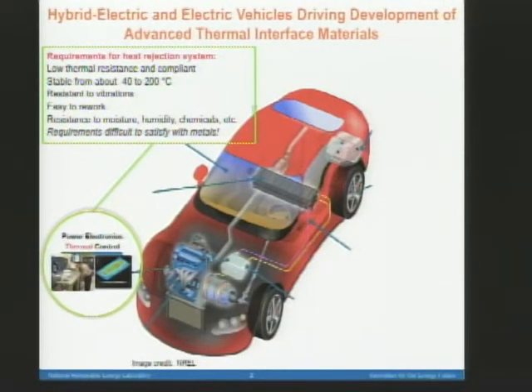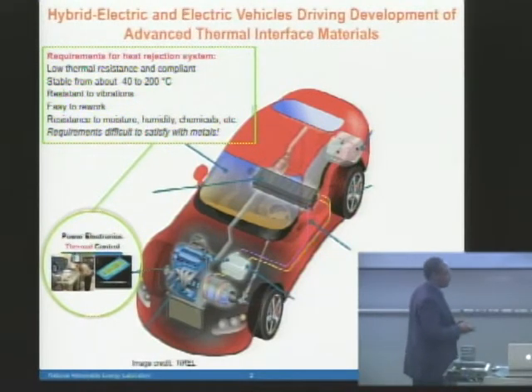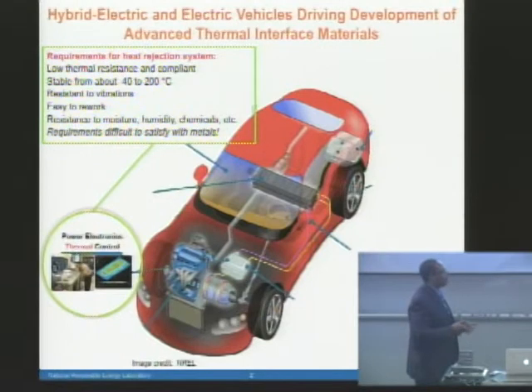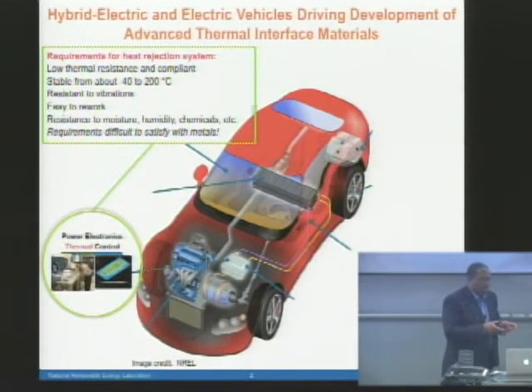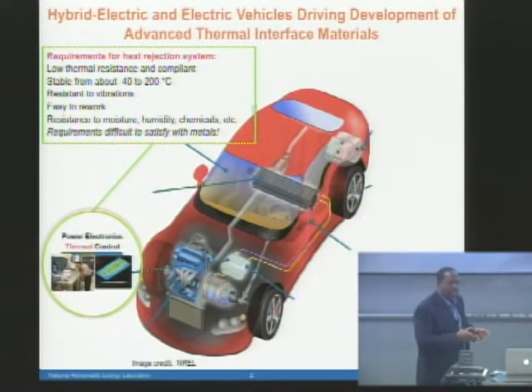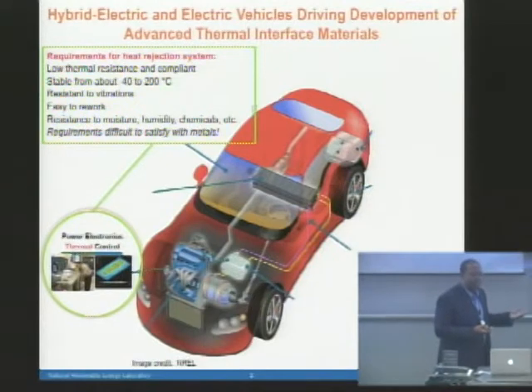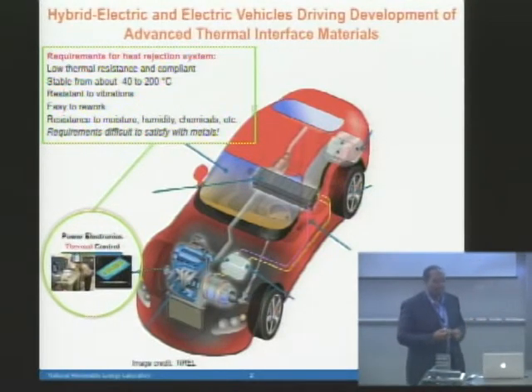In another application, again moving beyond the organic electronics, we start looking at devices such as hybrid electric vehicles. One of the biggest challenges in developing hybrid electric vehicles is developing more efficient power energy converters, or power inverters. There's a push right now to move to materials such as gallium nitride, so you can shrink the size of these power inverters by a factor of at least 5. The issue is that when you do that, you also go up in power density, and so now you have devices that can withstand 200 to 250 degrees C operating temperatures, but you have to have thermal materials that can handle not only the larger heat loads but those particular applications. And so we're looking at materials such as carbon nanotube thermal interface materials to go into these applications.